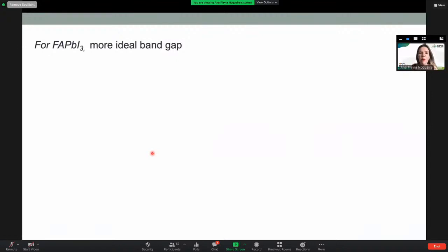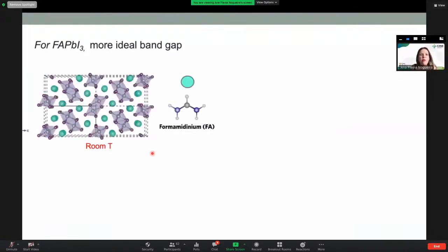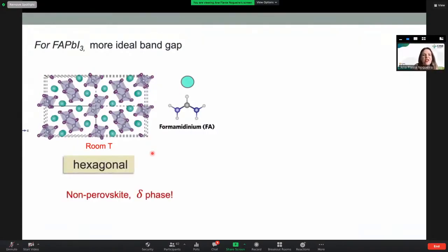Why am I talking about this perovskite? Because this is the perovskite with the most ideal band gap for solar cells. Let's say this is the holy grail of all the compositions. Everybody in the world is now really investigating this perovskite with only formamidinium. But what's the problem with this type of perovskite? Because at room temperature, or at least in the range of temperatures at which solar cells operate, we don't have a cubic phase. And if you remember, a perovskite has to be cubic. So this kind of perovskite is hexagonal. It's a non-perovskite phase. We call it the yellow phase, okay? And this phase is not photoactive.